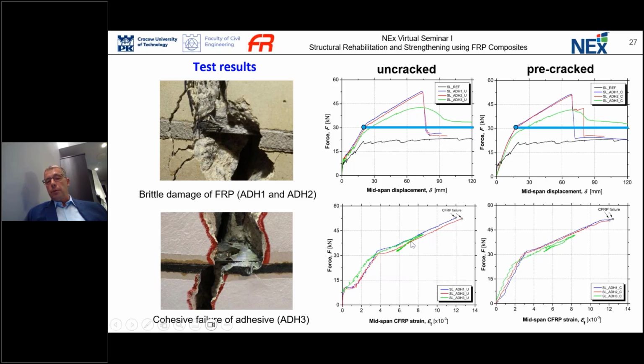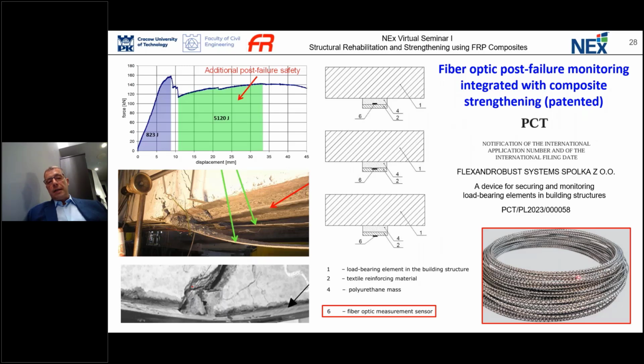This is also confirmed when we observe the strain measured on the composite material. So if we have such ability that we can apply this kind of flexible bonding, it is also useful to integrate it with some kind of fiber optic measurement system that can monitor the structure after failure. In this case, we give authorities post-failure information on how the structure works, if it is safe, if we can still use it, and what we can do with it.